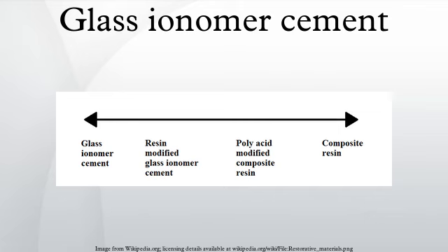Fuchs and others compared the clinical performance of a glass ionomer cement with amalgam in Class II restorations in primary molars. Only 9 of 101 glass ionomer restorations met all quality criteria after 1 year, whereas 90% of the amalgam restorations met all the evaluation criteria after 3 years.